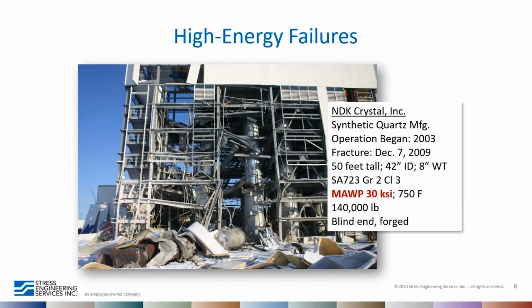This is a quartz plant, the NDK quartz plant. So they had a process for growing synthetic crystals. It's a very thick-walled vessel, and they would put quartz along with sodium hydroxide and various other substances under a very high temperature and hold it for about 150 days to grow quartz crystals.